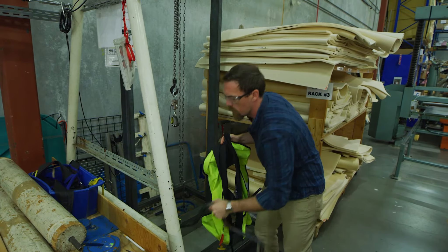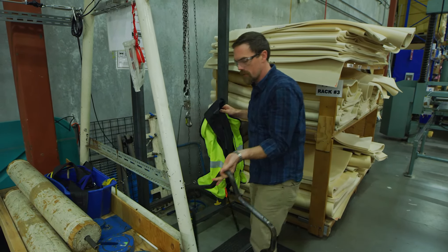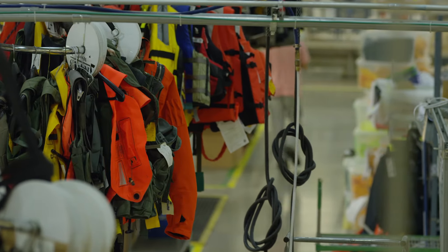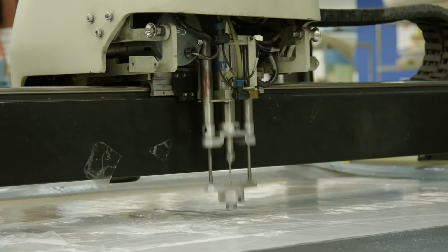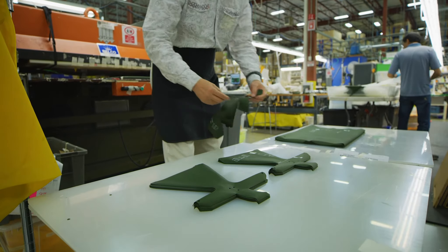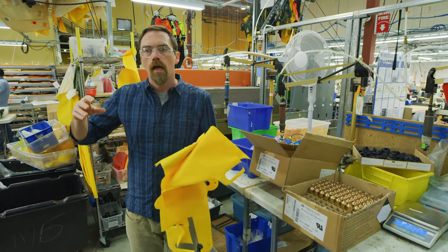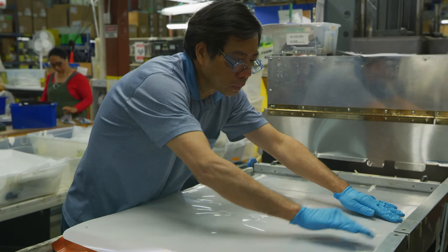We confirm that the bladder of the finished product as made can maintain the buoyancy for a minimum of five minutes after being submerged for six hours in water, and while still in the water. Other tests we do per lot involve strength testing, where we mount the inflatable onto a steel frame that resembles a human torso — we call this the gallows. We pull to a strength described by the standard in the file for the product, and while inflated, make sure you can grab the corner of the device and not tear it and not deflate it.